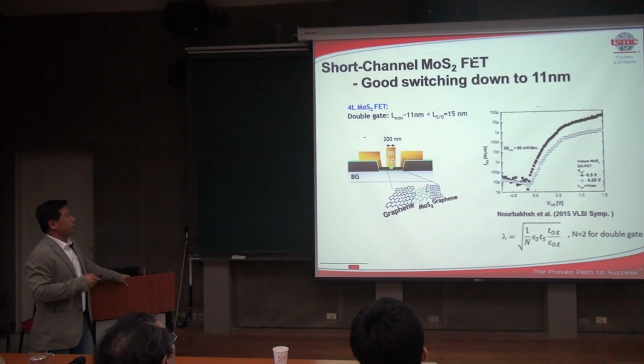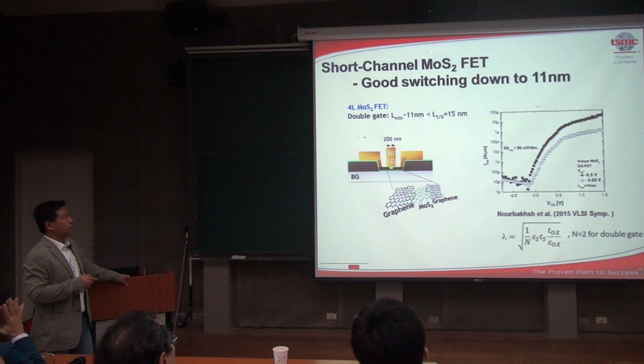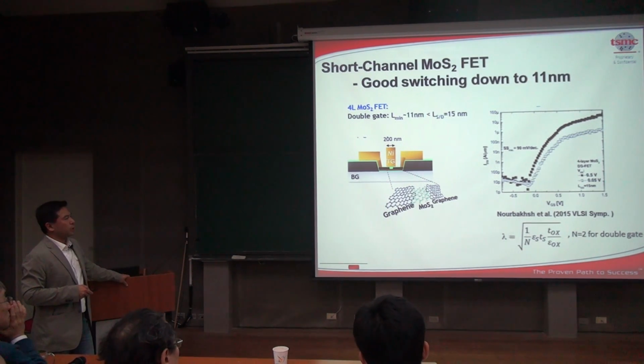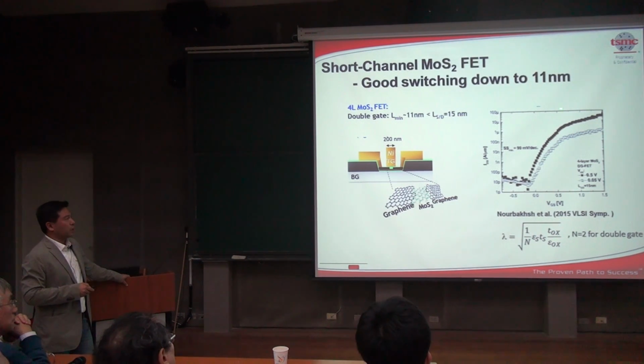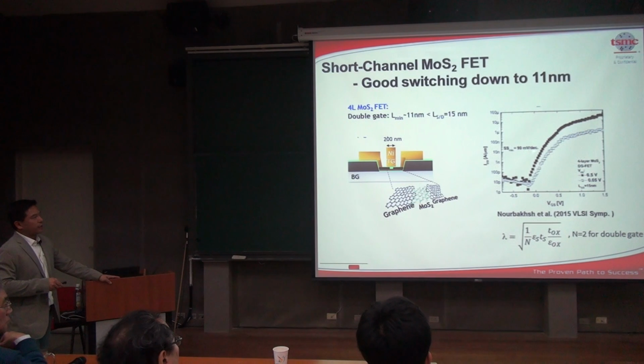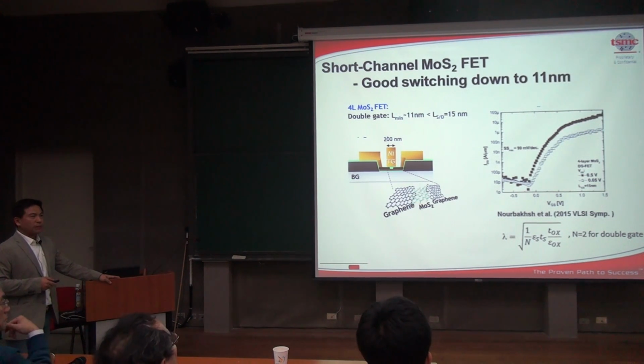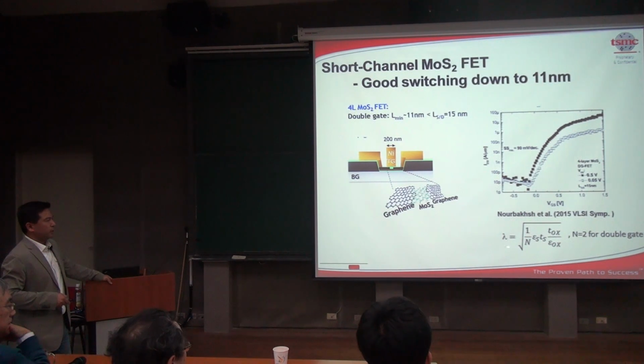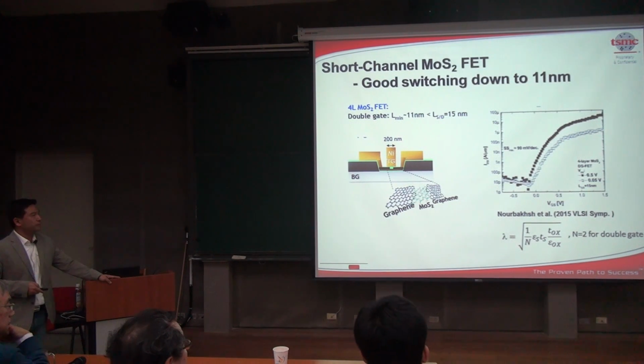A MOSFET based on 2D materials with a bandgap has been demonstrated. This is a work that was published this year in the VLSI Symposium that shows the MoS2 material with a gate length down to 11 nanometers, but still having a very good on-off ratio and a reasonably good switching slope. We'll talk more about this slope later, but for now just keep in mind that 90 millivolt per decade is a respectable number that shows that the switching is pretty good. It also agrees quite well with the projection, that the length is still much larger than five times the lambda.